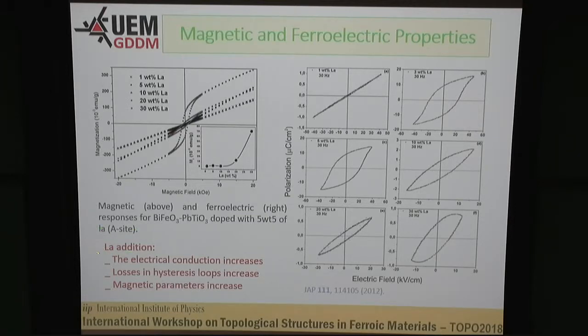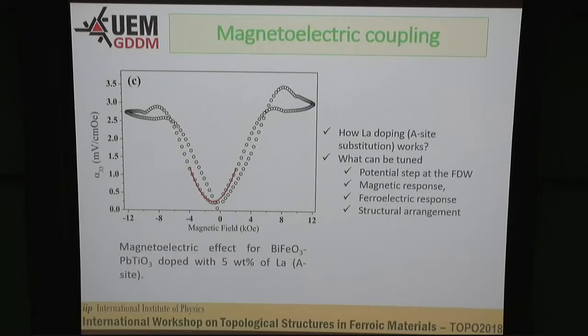What does lanthanum addition do in this case? It increases electrical conduction, and losses in the hysteresis loops also increase. You see here that this is not good. But on the other side, the magnetic properties also increase. We did some magnetoelectric characterizations, and the magnetoelectric coefficient is one of the highest for single-phase materials that you see, in the sample with 5% of lanthanum.